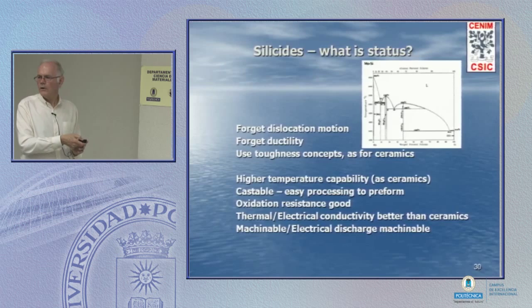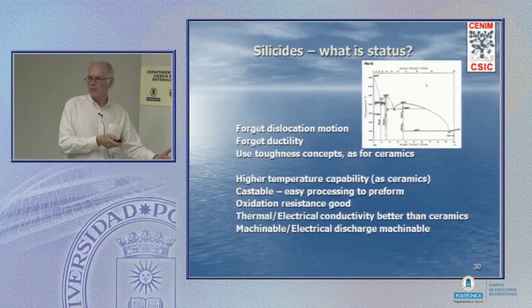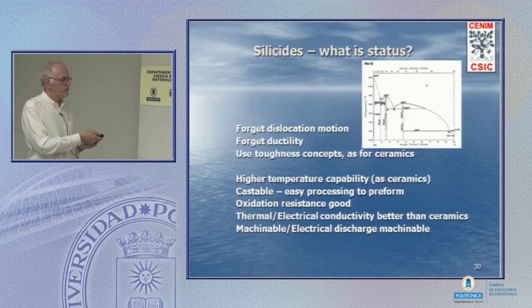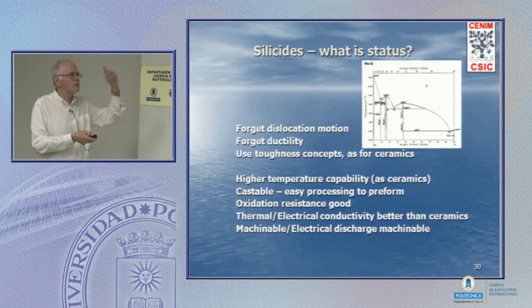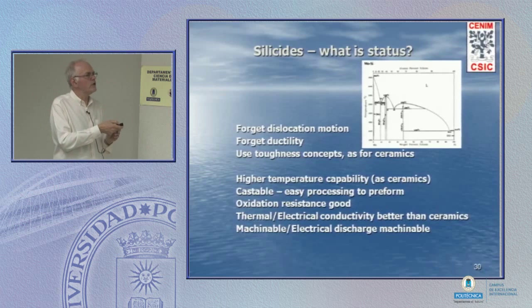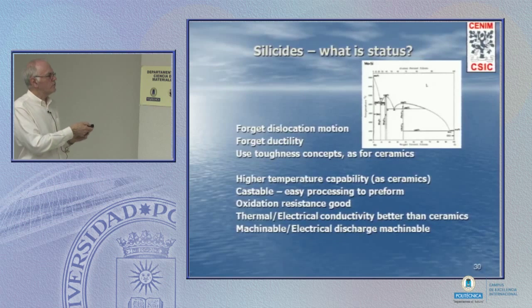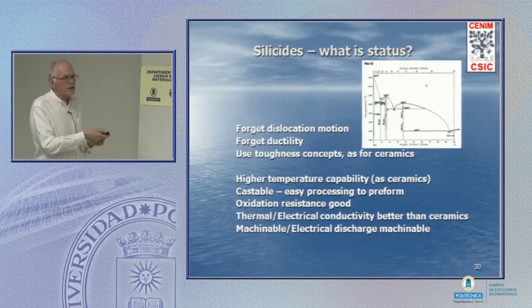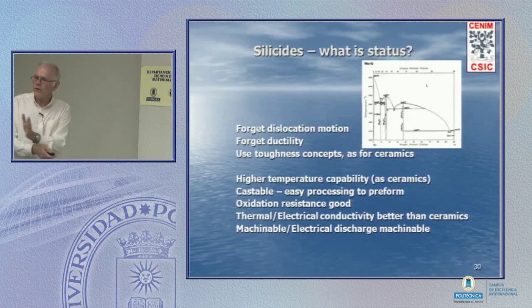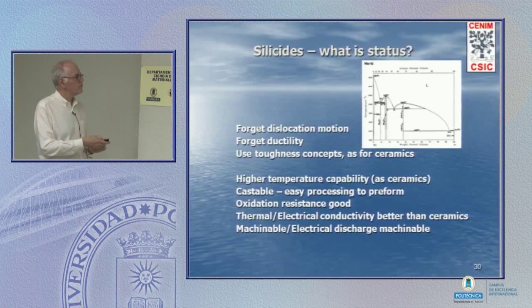High thermal conductivity means that you can cool them actively, which is a significant gain over the ceramic. Electrical conductivity means that they can be electrical discharge machined, as you cannot with ceramics. They're castable, they are metallic alloys. You can mix them up in the liquid state and cast them to shape. Oxidation resistance, very good. And we're moving further than TiAl towards ceramics.